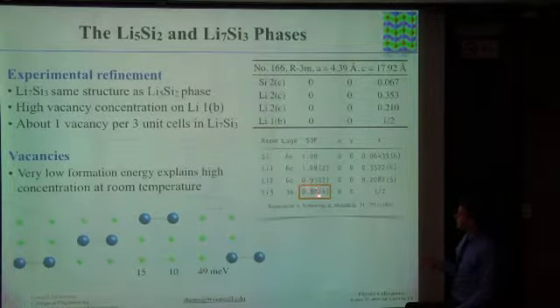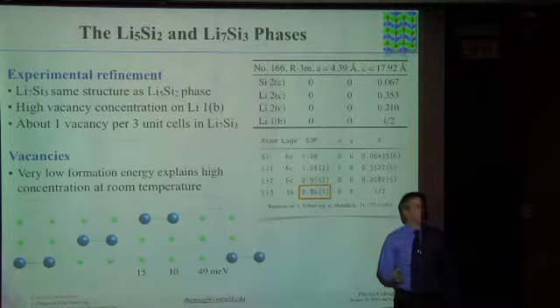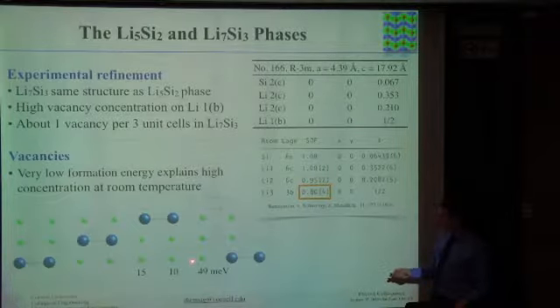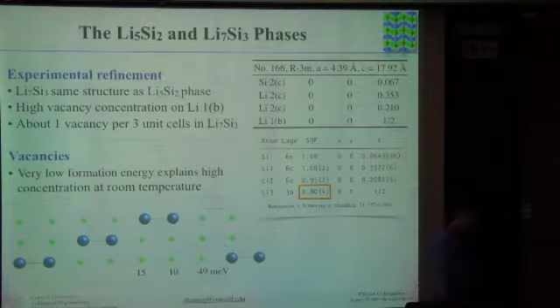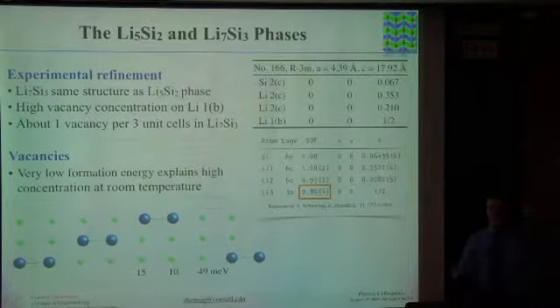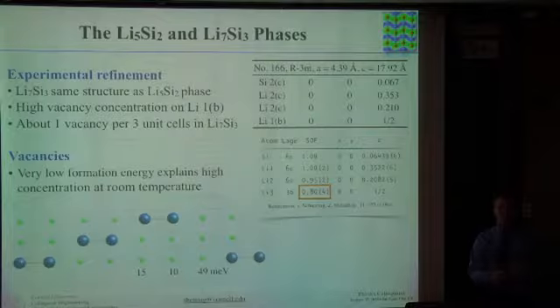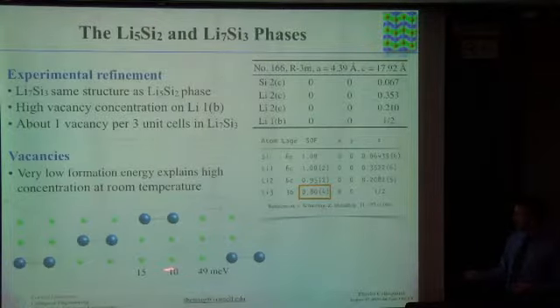And so this site is only occupied 80%, this is occupied 95%. These are very unusually high vacancy concentrations. So we thought, oh, let's take a look. Why is that high? So we calculate the vacancy formation energies. And I'm not sure if any of you have an idea of what a typical vacancy formation energy is. But for example, in silicon, the energy to create a vacancy is 3 electron volts. In most metals, it ranges from half an electron volt to about 1 electron volt. In this metal, the vacancy formation energy isn't even measured in electron volts. It's milli-electron volts. This is 10 milli-electron volts, 15 milli-electron volts, 50 milli-electron volts.